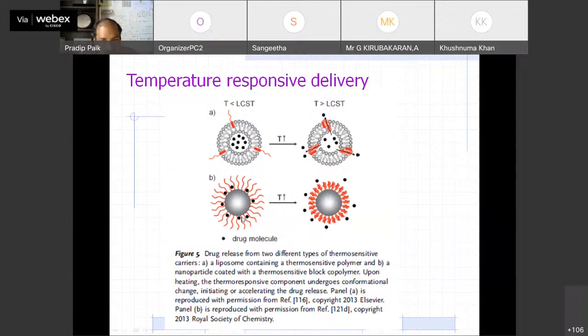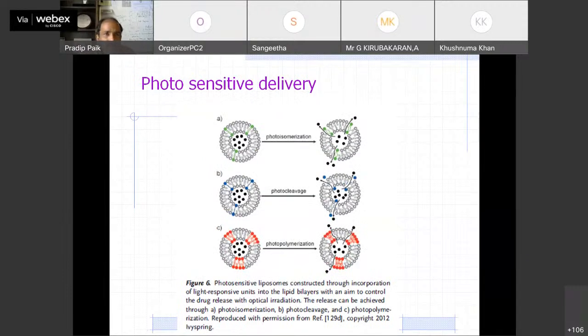So in these cases, there is a core, the polymers, and then let's say a brush-type network on the surface. Inside the brush or polymer chain network structure, you can entrap the drug molecules. Okay, and here the stimulus is temperature. Whenever there is a temperature stimulus, these polymer brushes on the surface will change the network structure. They will vibrate. Let's say there will be secondary emission of light, or secondary agitation will be created, but vibration will be created, which will help the drug molecule to go out. So these are the advantages of the core molecule.